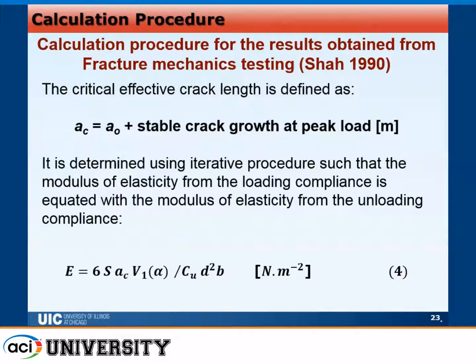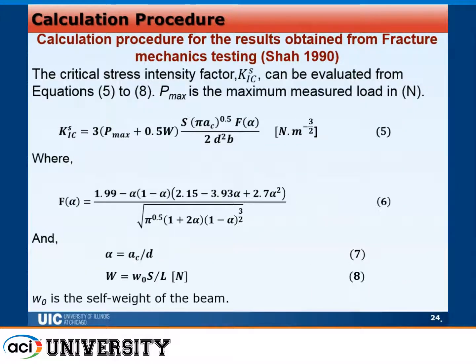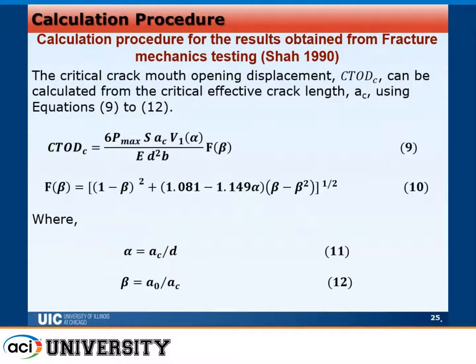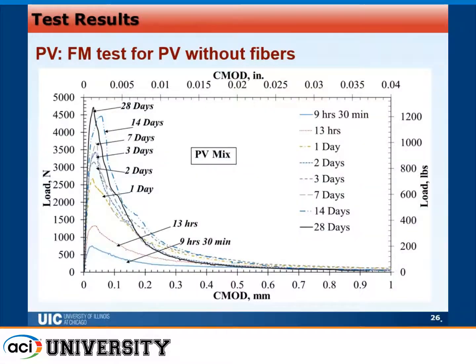You will equate the E, the modulus of elasticity of the unloading, and the modulus of elasticity of the loading, and then after that you will be able to calculate the critical crack mouth opening displacement and the stress intensity factor. Typical values for the PV without fibers, as you can see, they fail and stop at around 1 millimeter here, which is 0.04 inches.